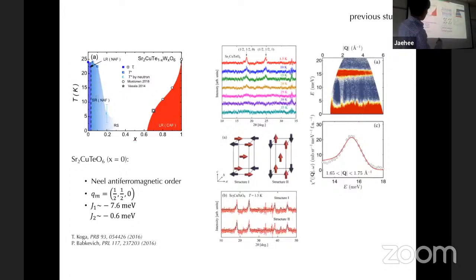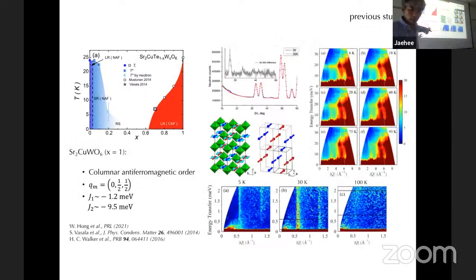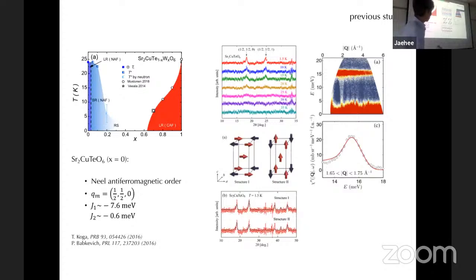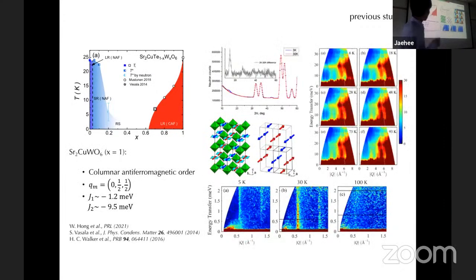So these are experimental data for the two endpoints, tellurium and tungsten. And one thing I want you to remember is, of course, as long as you have this long-range order, if you measure the magnon spectrum, you have this very nice collective magnon spectrum. Okay, and same thing for the tungsten case. All right, good.